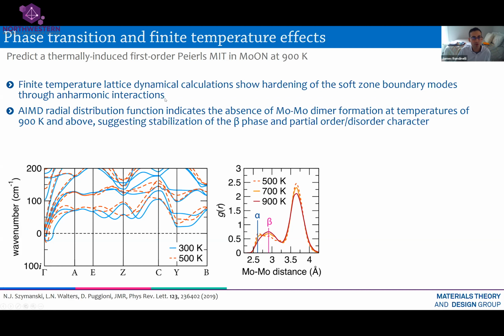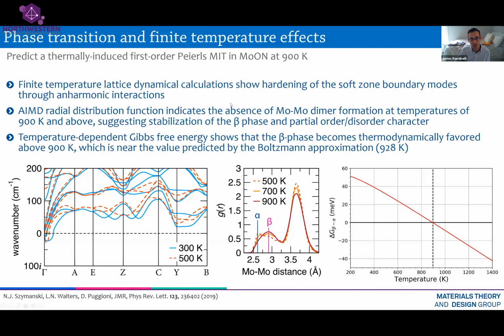And then we also computed the formation free energies of the two competing phases. And what we are predicting is that this material would exhibit a phase transition somewhere around 900 Kelvin. So vanadium dioxide exhibited a phase transition around 350 Kelvin, niobium dioxide, so these are two oxides, exhibited a transition over 1,000 Kelvin. And this material, molybdenum oxynitride, is around 900 Kelvin. So this is the prediction.